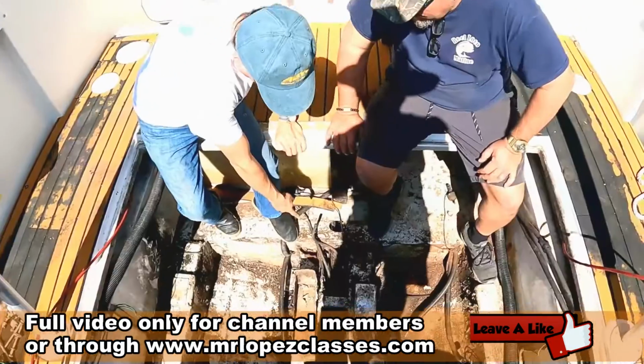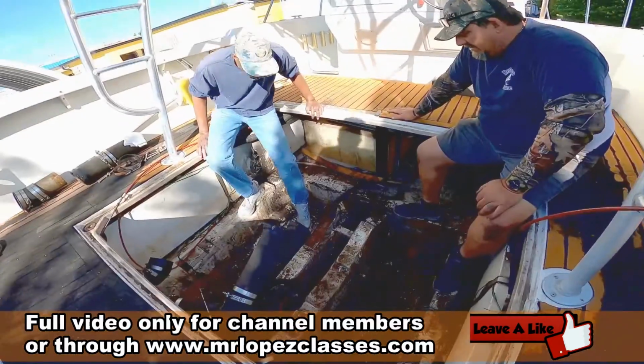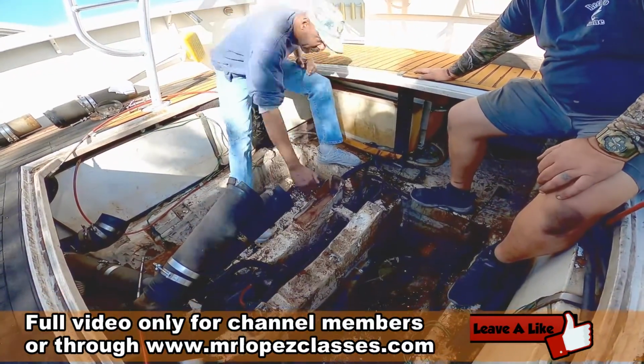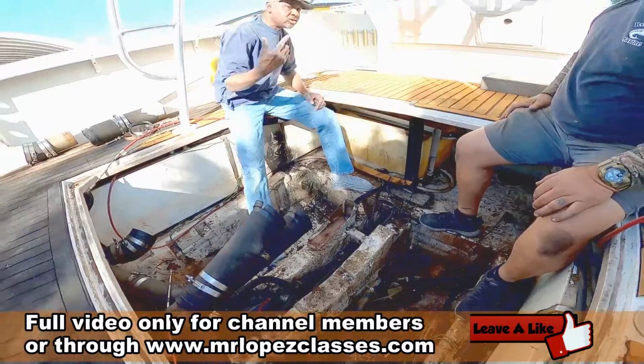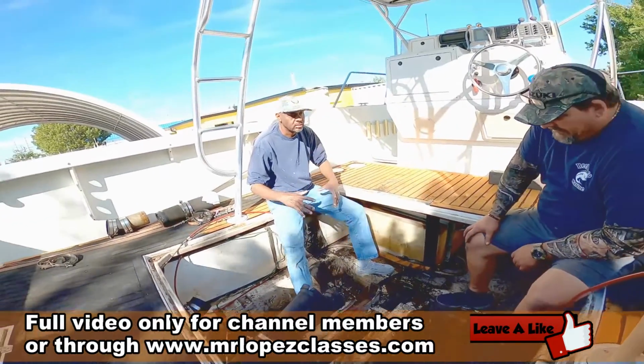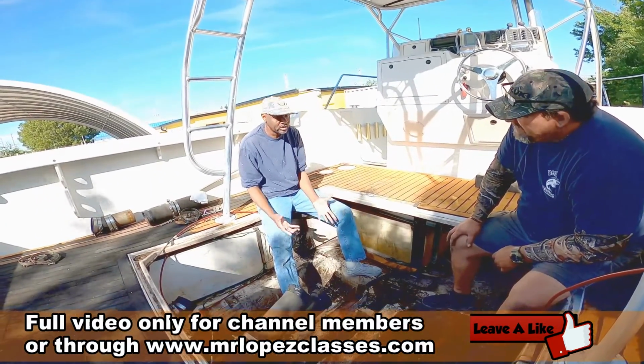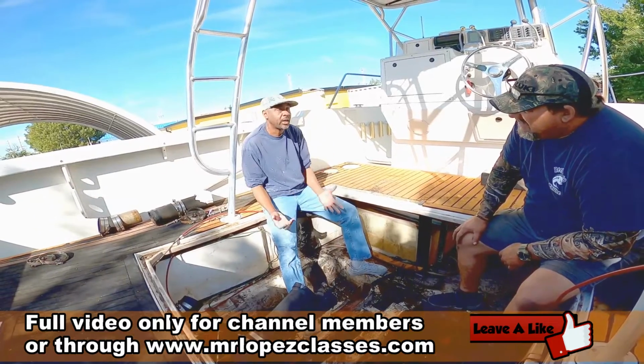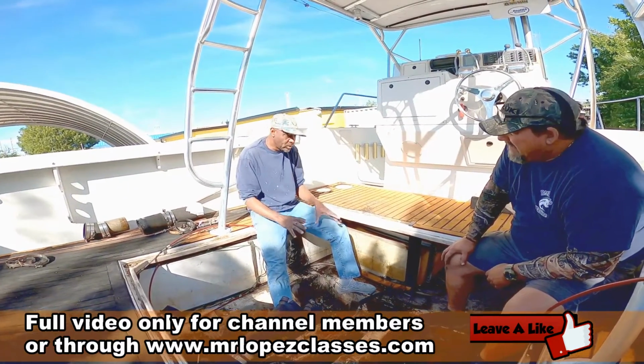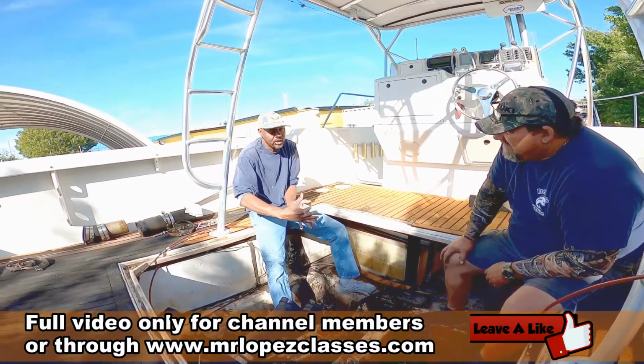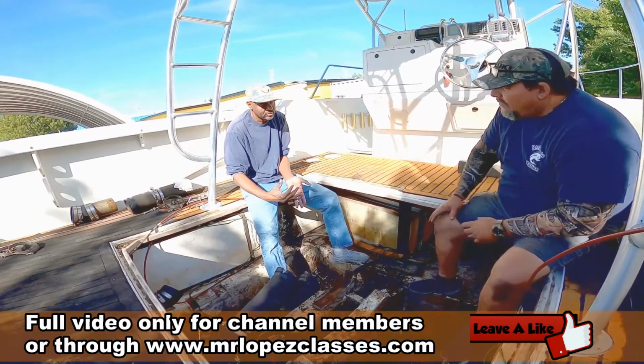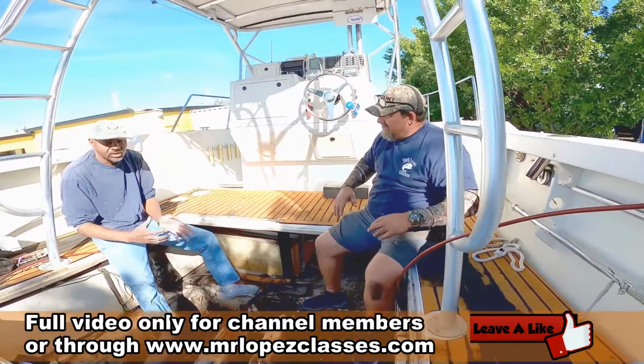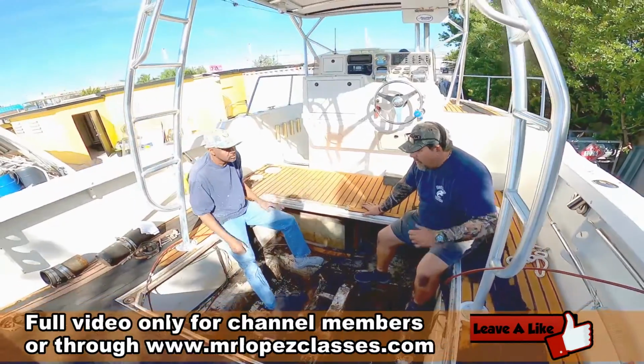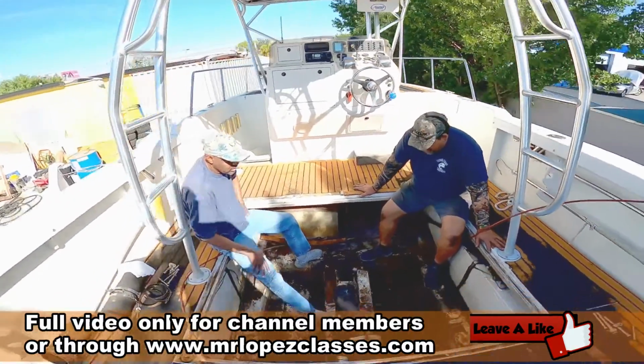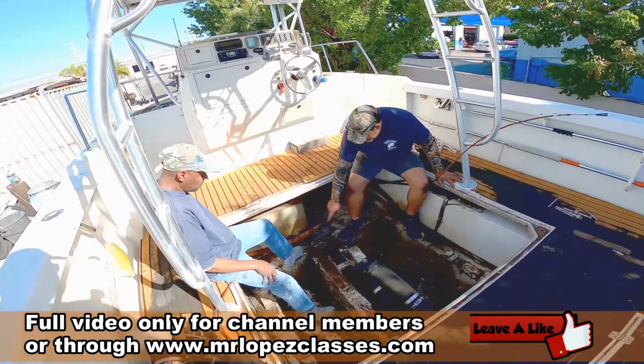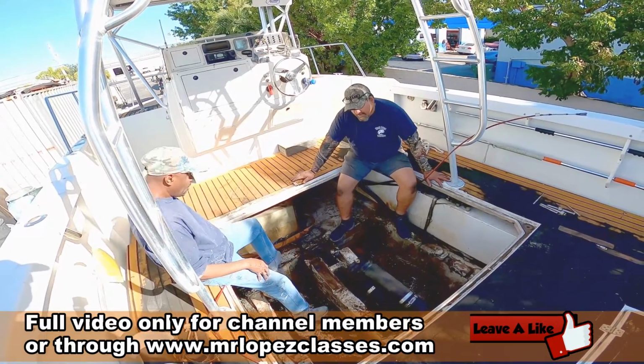It's completely gone. Yeah. And how we determine bad stringers, you tap on it and you listen to the sound, where you can tell that the inside, which is the core, the main strength, is bad. Right. So basically what's holding it is just the outside fiberglass that laminates the outside. Is that why the boat's buckling on the sides? Yeah, because there's no strength, no support down the middle of the boat. And I see this rotted on the inside, like these holes here, you know.